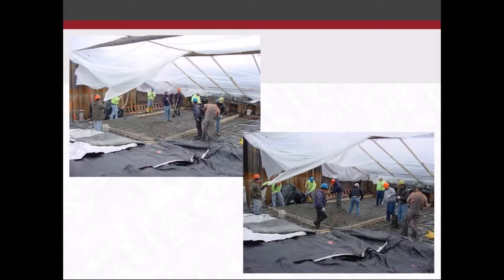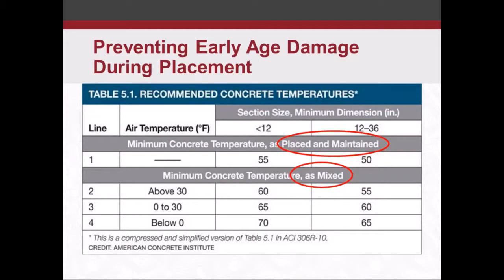A couple more pictures from the project that was on Lake Champlain. In these two pictures they're actually taking the curing blankets off of the subgrade because they had the glycol lines. You can see some of them right here. They had these glycol lines on the subgrade to make sure that the subgrade was thawed, and then they put the curing blankets over the glycol lines, thaw out the subgrade, peel the blankets back, peel those glycol lines back, and then place your concrete, and then you can put the lines and the blankets right back on the concrete.